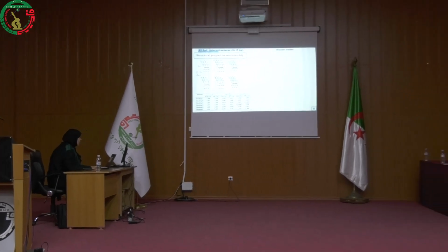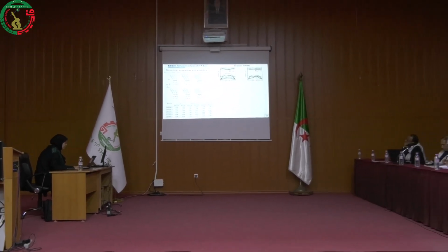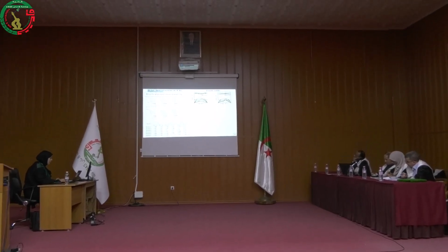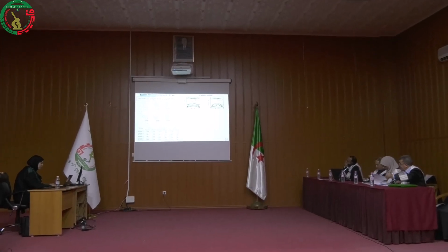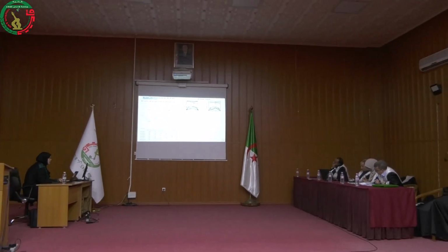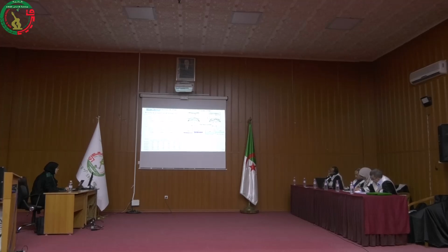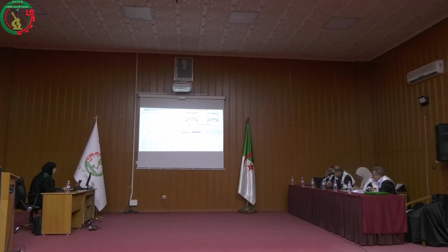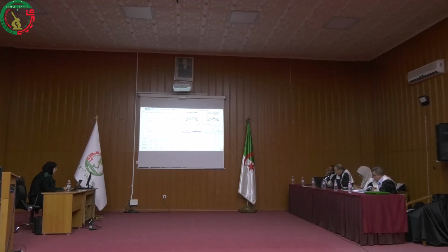As summarized in the table, to assess the dynamic stability, phonon spectrum analysis was performed, which confirmed the dynamic stability of the studied heterostructures. Thermal stability was evaluated via ab initio molecular dynamics simulation at 300 and 500 Kelvin, demonstrating minimal thermal fluctuation without structural transition, confirming their thermal stability.